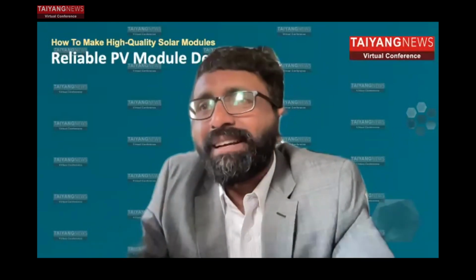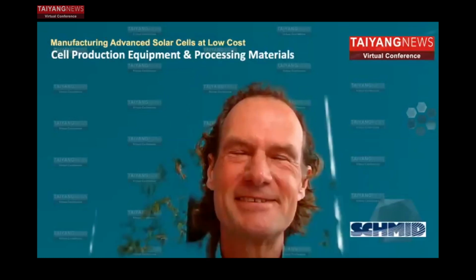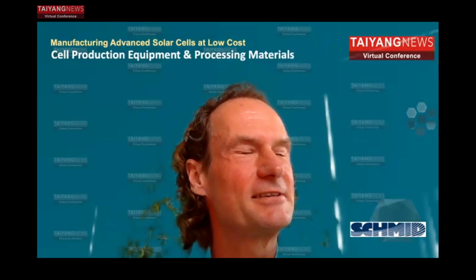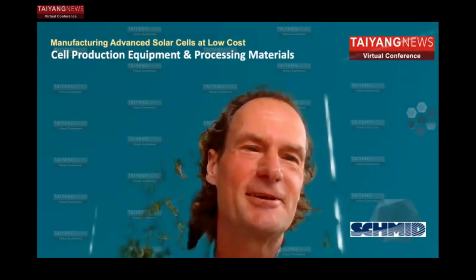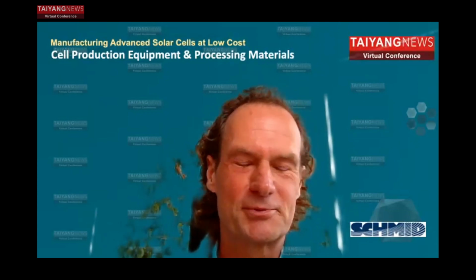Okay. And here there is one more tricky question. Do the weak wafers that survive the inline process break at a later stage? No, actually, the funny thing is we've seen that there is a region in the wafer thickness, around 140 micron, 130 micron, where the wafers are even more brittle than they are below 100 micron. So I would claim that the very thin wafers are pretty flexible and do not break later, if you don't impose processes that would break them, of course. But I would claim that the breakage added throughout the process to thinner wafers is less than, let's say, for wafers that are around 140, 130 microns.